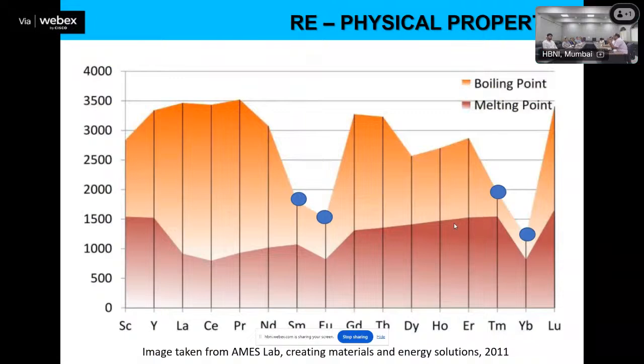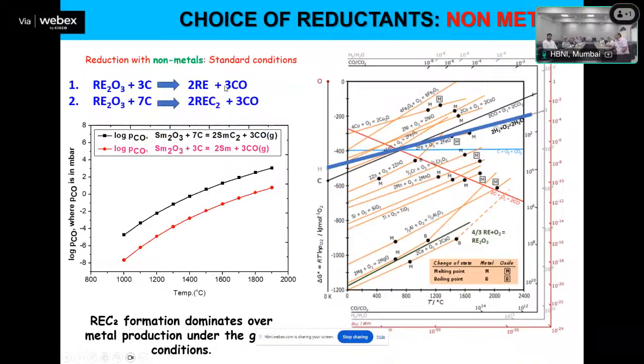So what is the plan, how can you obtain these four typical materials? Let us slowly develop a concept. If you want to reduce a metal oxide, what will you do? Like iron, you see whether it can be reduced with carbon, whether it can be reduced with hydrogen. This is the Ellingham diagram, you might be aware of that. It basically gives the relative stability of oxides with temperature. Whoever is lying lower is more stable, and whoever is lying higher is the least stable oxide.